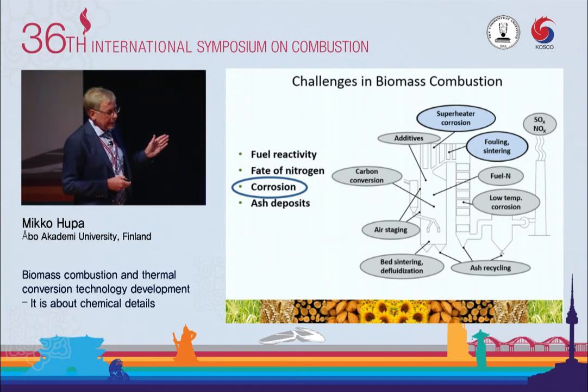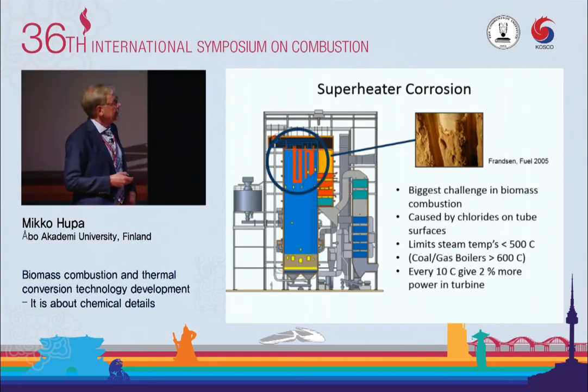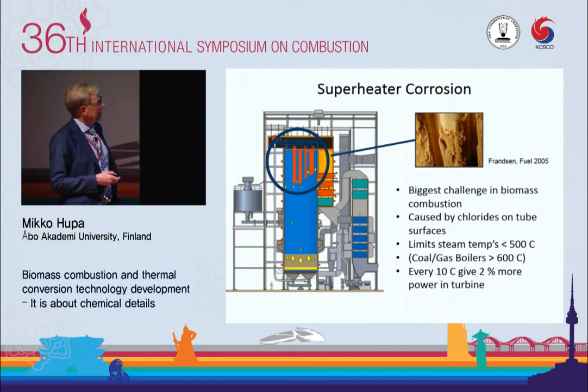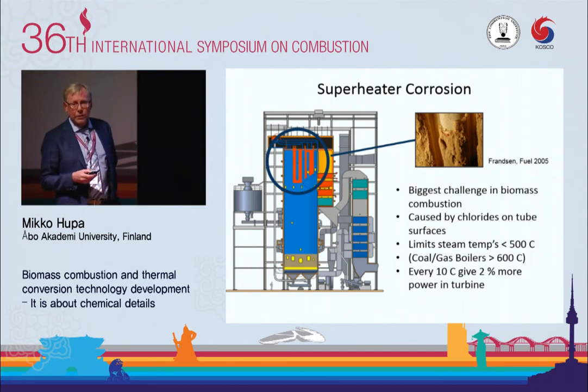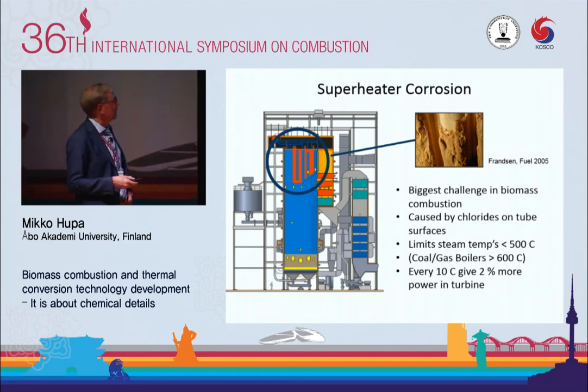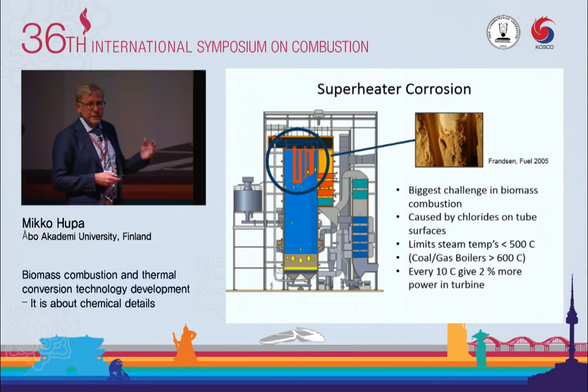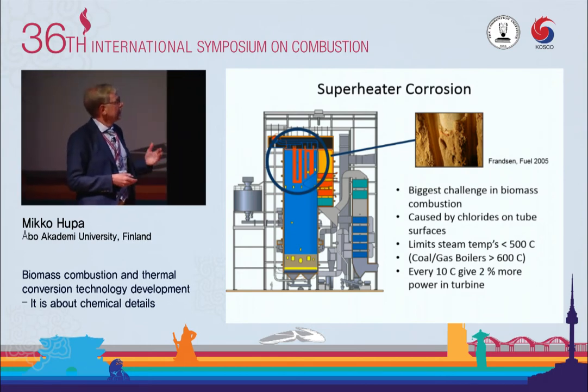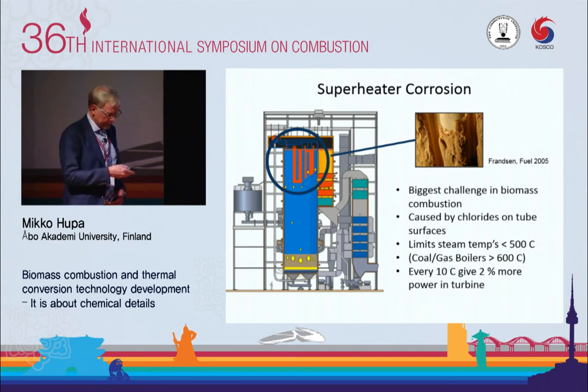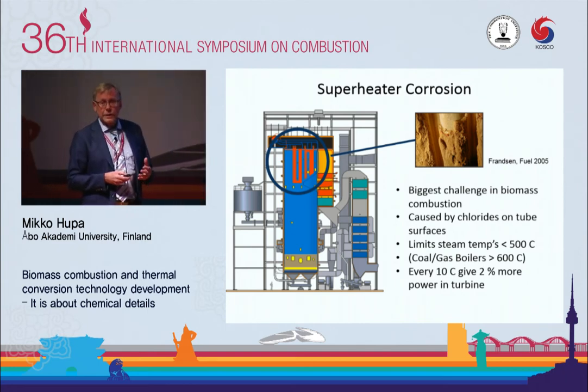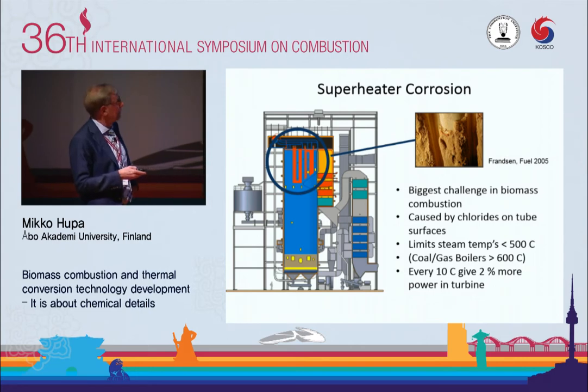Corrosion, a very important part of biomasses. And in fact, that's the biggest challenge in the technology development for these boilers. It's caused by chloride on tube surfaces. That's quite clear. There everybody is agreeing. But then I will tell you later that we don't agree about all the details of this corrosion. This is the reason why the steam parameters are much lower in even the most modern power plants of this type.